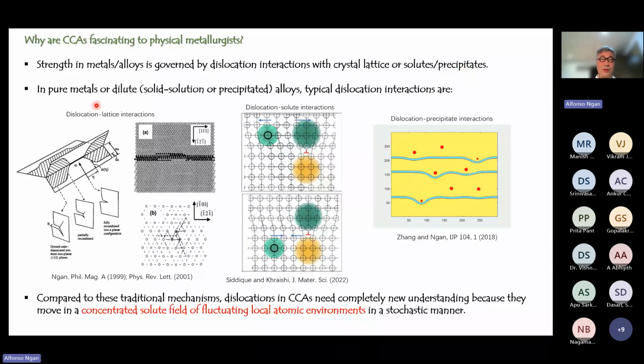So in pure metals or dilute alloys, the typical dislocation interactions are of these three types below. You could have dislocation core interaction with the lattice. Let's say if the dislocation core is not planar, then you would have to overcome this non-planar interaction, and therefore usually we would have the kink-pair mechanism. So that would be a critical stage for movement of dislocation in high purity metals.